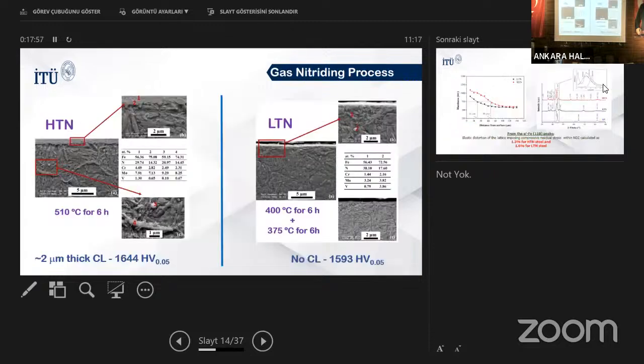Anyhow, we made some experiments. In our lab, we nitrided at 2 different temperatures, this one and this one. I don't want to give you the details. This one, which we called high temperature nitriding, provided a compound layer thickness of 2 microns. But the one applied at lower temperature was compound layer free, but still hard. The hardness of this surface was 1,600 in the absence of compound, and in this case 1,650 in the presence of compound. So we have 2 samples, high temperature nitriding and low temperature nitriding.